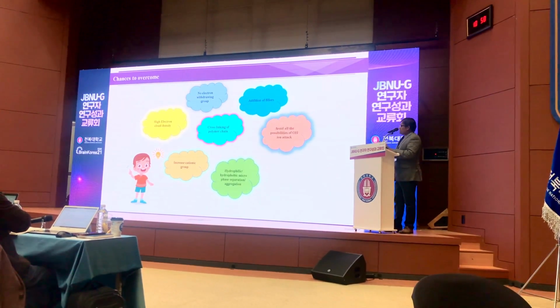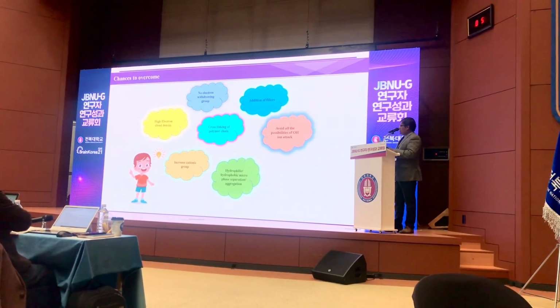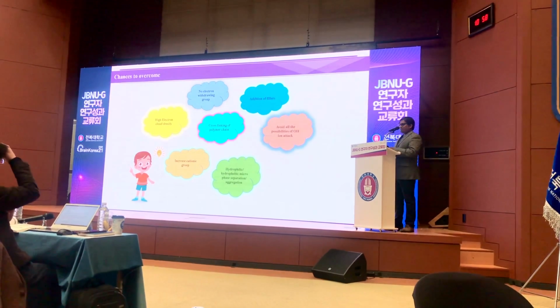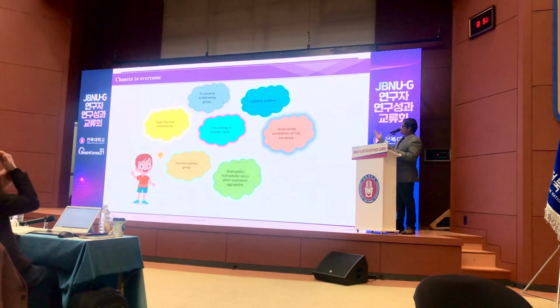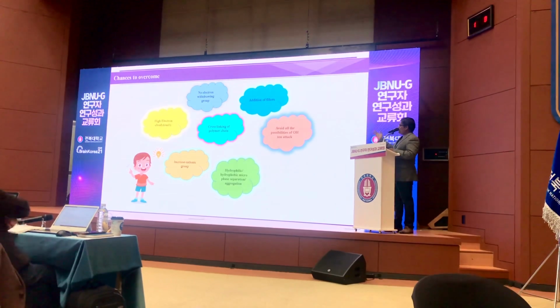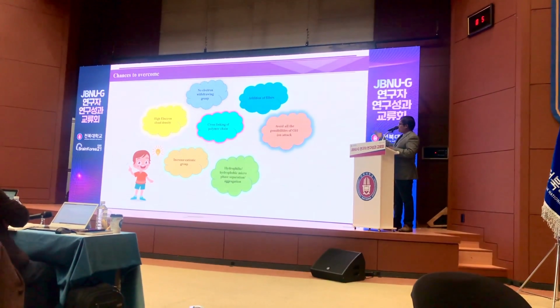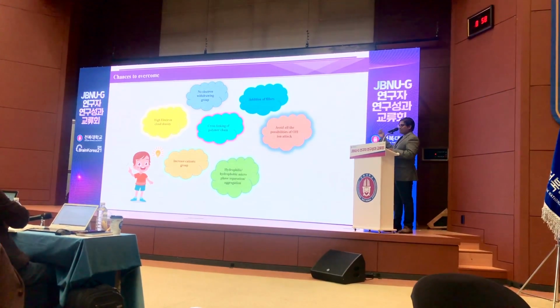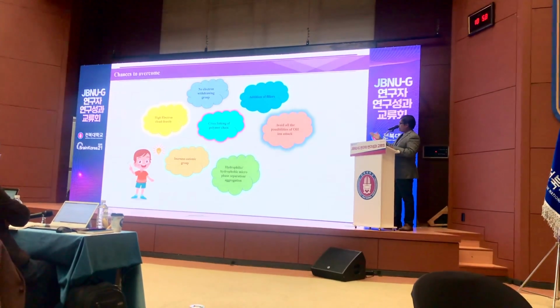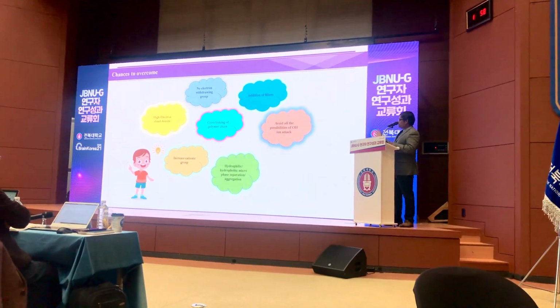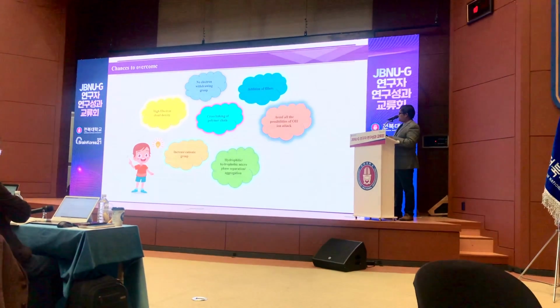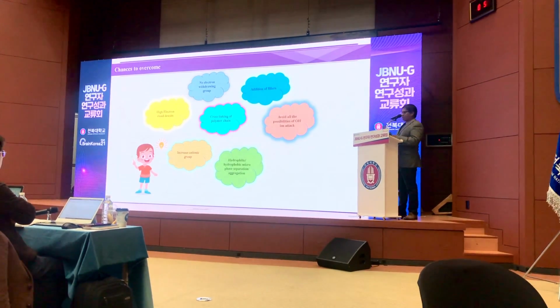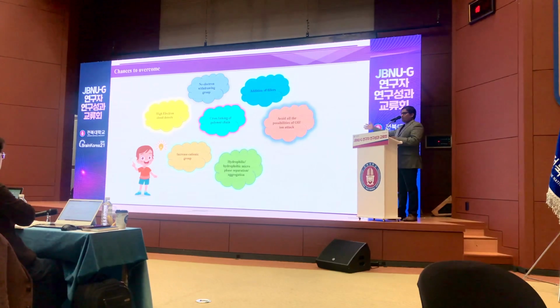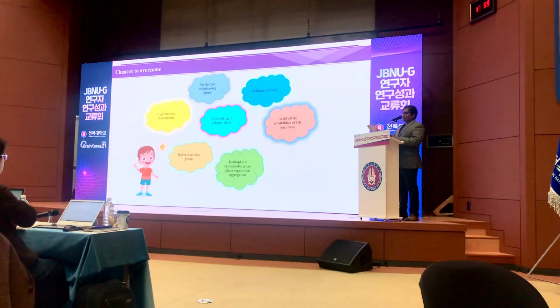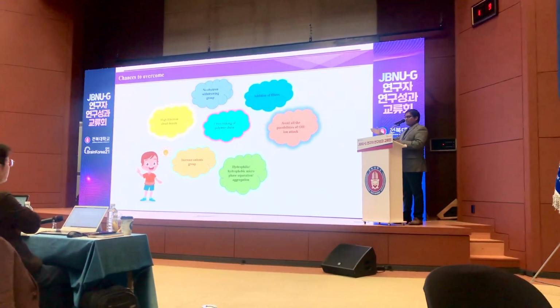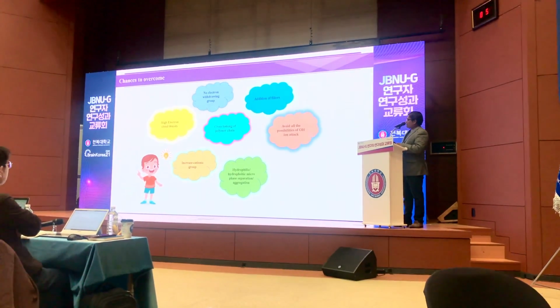So by having all these ideas, we can make the very best anion exchange membrane. You can see these are all the ideas. Let's say high electron cloud density, no electron withdrawing group, addition of fillers like graphene oxide or graphene nanofiber, cross-linking of polymer chains, avoiding all possibility of OH minus attack, and having hydrophilic-hydrophobic microphase separation. If we do all these things, we can have a very good anion exchange membrane electrolyte, and we can use it in fuel cells.